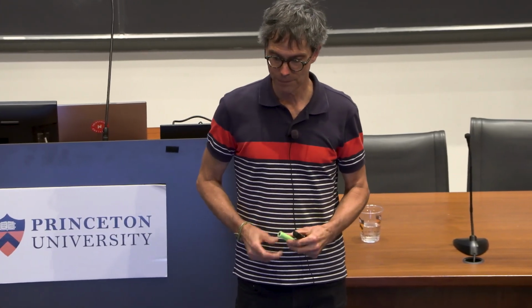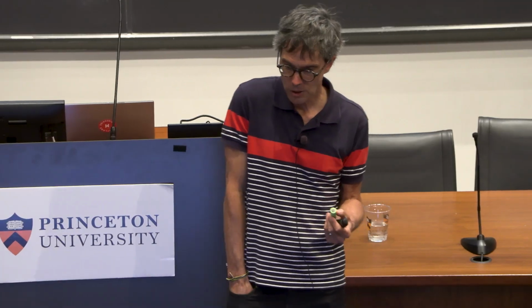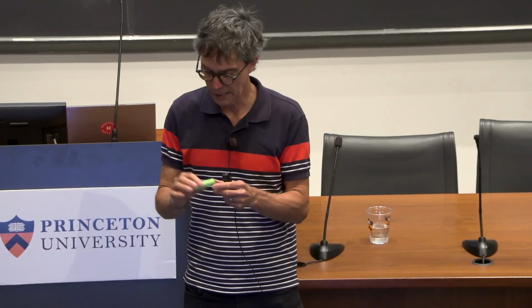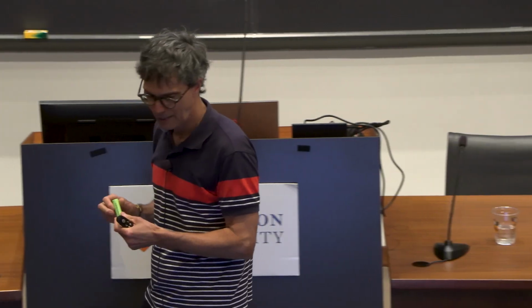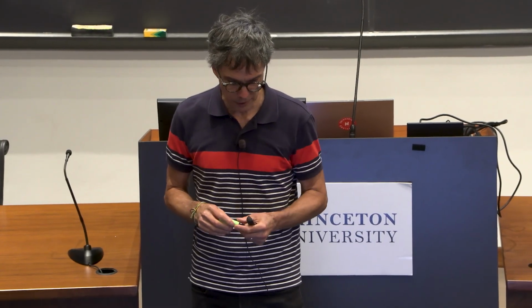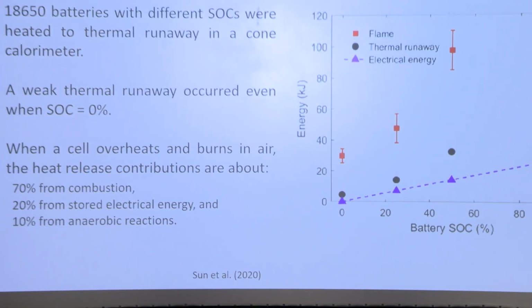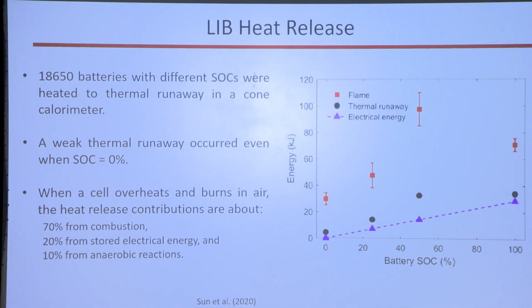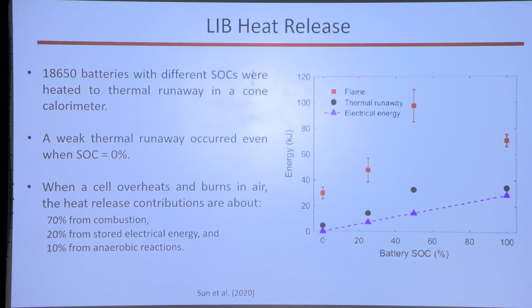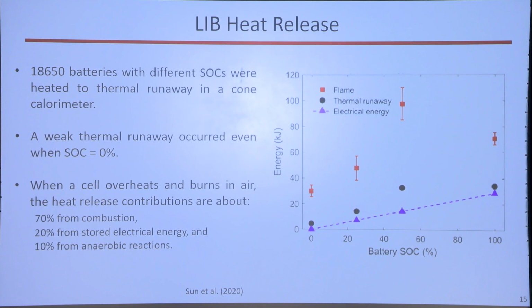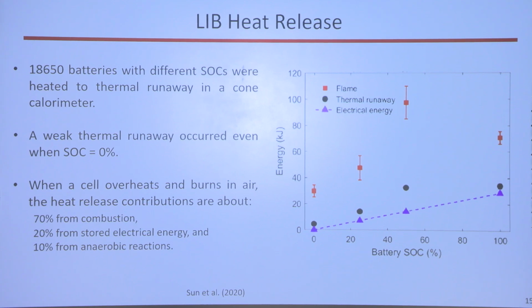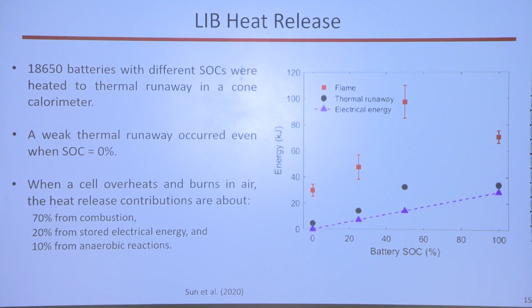So I tried to do research and to understand how much heat is released when an 18650 battery like this burns, and it's not very easy. So the best plot I can find is from 2020 here, Sun et al., where it's a plot of the energy that's released versus the battery state of charge. And if you look down at the bottom here, state of charge of 100 and the purple triangles, you can see really it's the only data that's nice and linear. So for a state of charge of 0, of course, there's 0 electrical energy. For state of charge of 100, it's somewhere around 30 kilojoules. So that's a nice straight line.